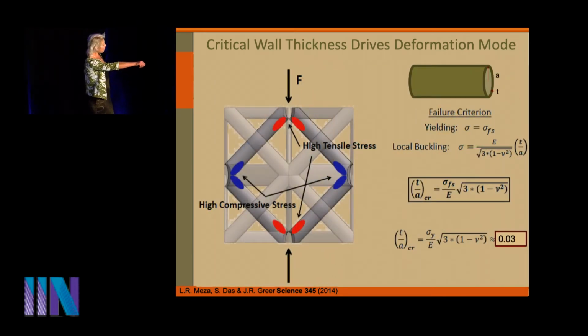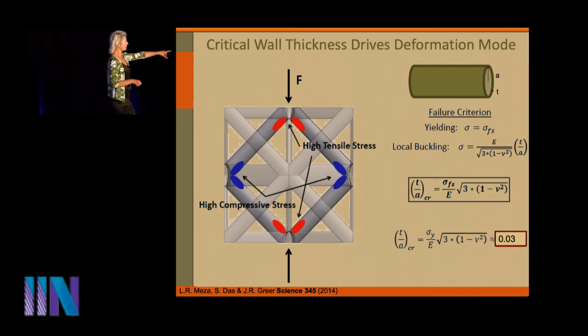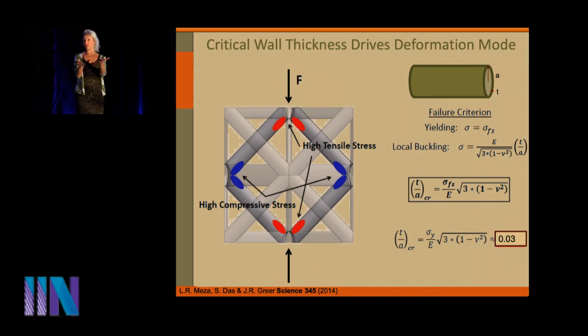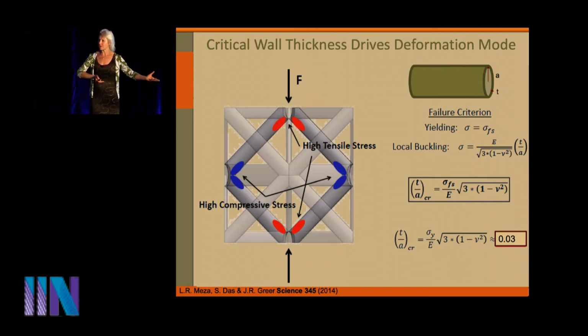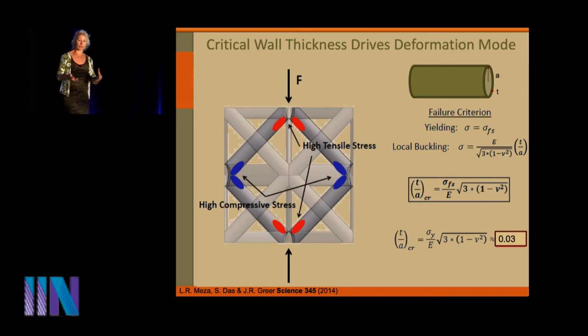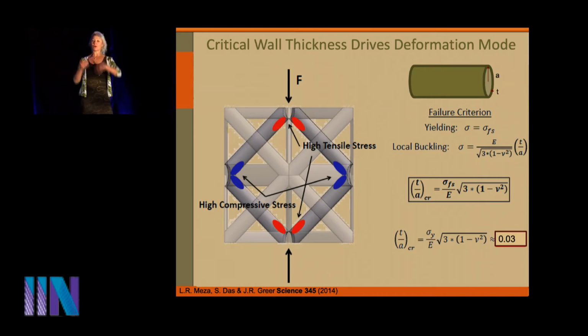So if you look at an individual beam whose radius, for example, is A and the wall thickness is T, there's a T over A ratio, basically how thin-walled this cylinder is, which can be compared to the fracture strength of your material, the failure strength when this alumina would fracture. It turns out that for this particular material, the critical ratio is 0.03. So for geometries below this ratio, we should be able to observe shell buckling. For geometries where it's higher than that, it would fracture before. So let's see if that's what happens.